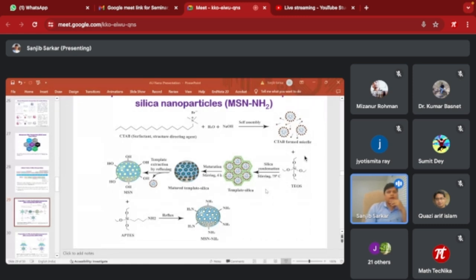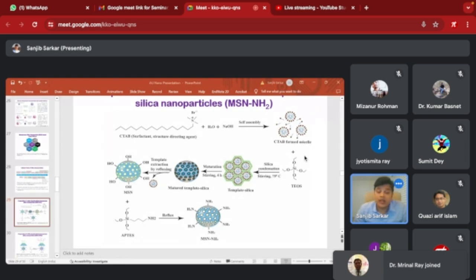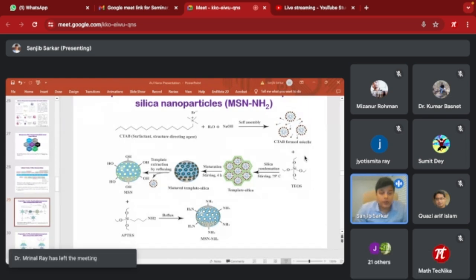So cytotoxicity is the key issue in the use of nanoparticles. Therefore, we use a cytotoxicity assay to determine the toxicity of the nanoparticle. Here we tested two types of cells: one is C2C12 and another is a mammalian liver cell. That is, one is a muscle cell, another is a liver cell. Both are mammalian cells. We found that up to 200 microgram per ml, there is no significant cytotoxicity in both cases, in low glucose and in high glucose conditions.